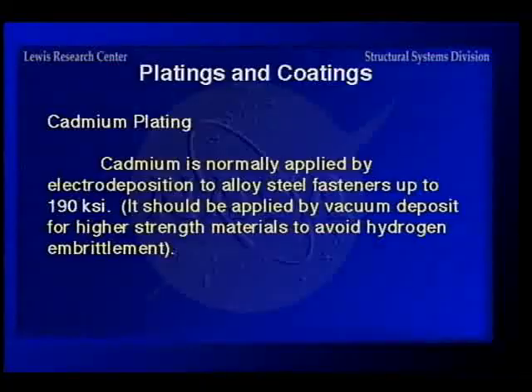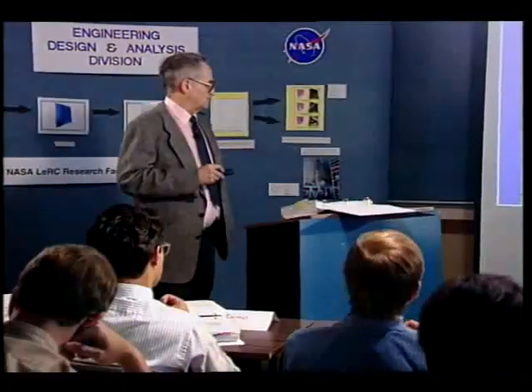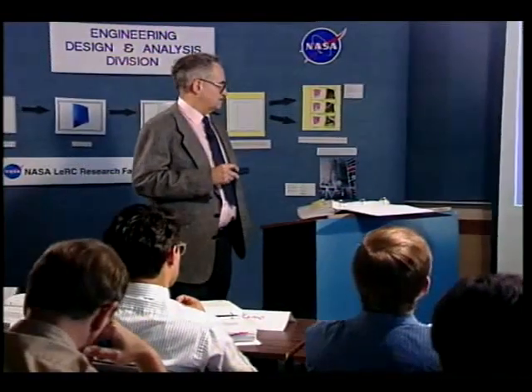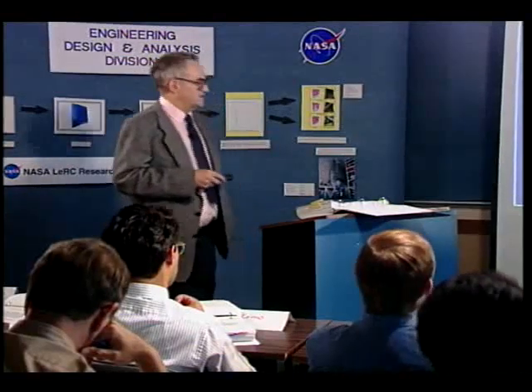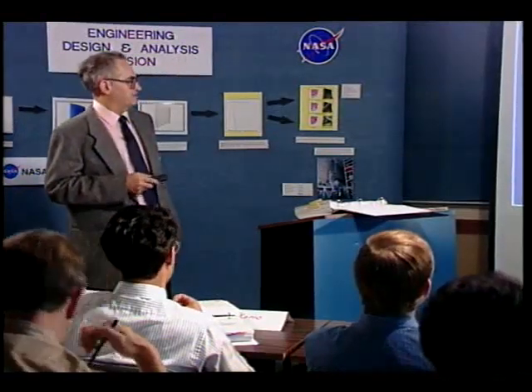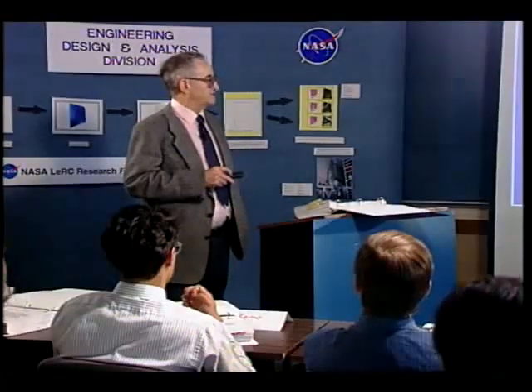electrodepositing alloy steel up to 190 KSI. If you get above 190 KSI, then you can't prevent hydrogen embrittlement, and you have to go to a vacuum deposit, which runs the cost way up. Now, here's something that is overlooked a lot and causes lots of problems. When parts are cadmium plated, they have to be baked within 2 hours after plating. And the reason I said 8 to 23 hours, it depends on who's baking them or if any baking is done, because I have heard of cases in which no baking at all was done to bake the hydrogen out.